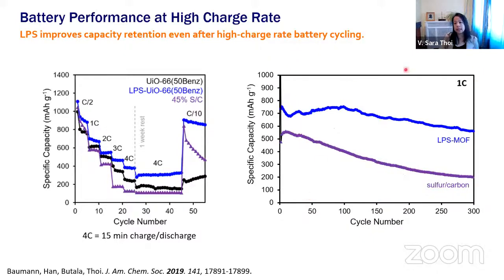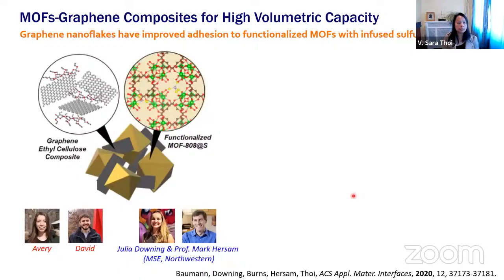We also see that if we discharge our batteries at relatively high charge rates, we still see high performance even after large cycle numbers. So we took this idea and we thought, well, what we need is not only to optimize for gravimetric energy density, we also need to optimize for volumetric capacities. And so we teamed up with Professor Hersam at Northwestern and his student, Julia Downing, to look at other ways to make a battery composite.